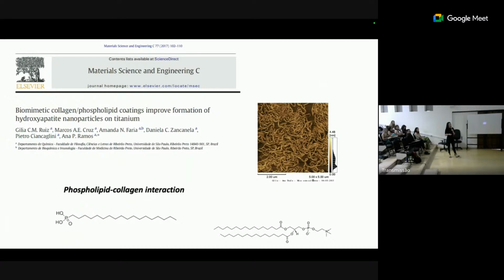We can improve this model also by adding proteins to the surface of the phospholipid films. In this study, we modified the surface with the lipid films, and we also added collagen to the structure.